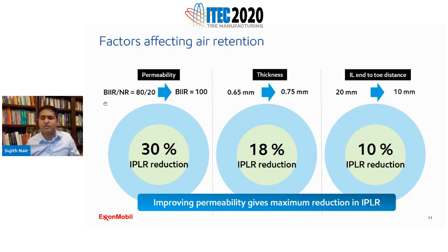So we tried an experiment where we went from 20 millimeters, so a 20 millimeter distance of the inner liner ending to the toe of the tire, to 10 millimeters. So you're going closer. And we saw that there is a 10% improvement in the IPLR.